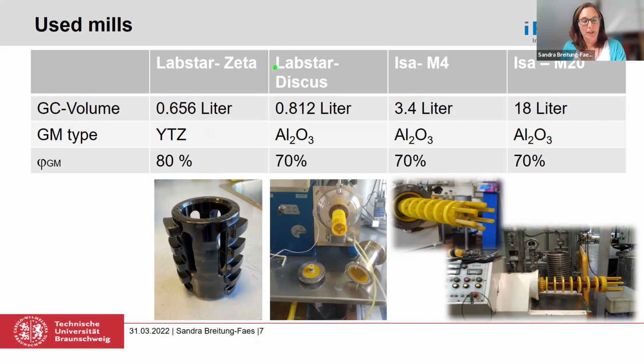Later on, my coworker David used the LabStar Discus geometry for a certain industrial project. It looks in principle like a disc mill. Maybe it cannot be seen so well here. And at the end, you have something like a cage, a separation system for the grinding beads. The grinding chamber volume is a little bit higher, and here we used alumina beads because it was minerals grinding and much coarser.